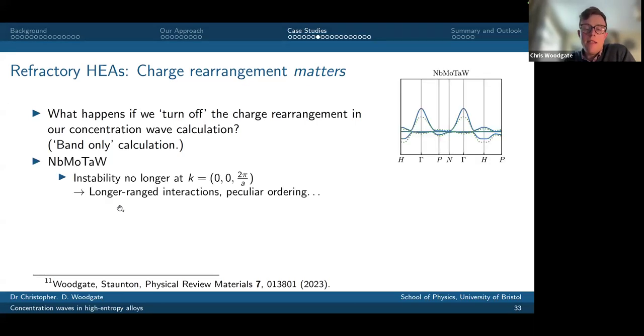And if I go to niobium, molybdenum, tantalum, tungsten, what I find is if I turn off the charge rearrangement, the ordering temperature is not particularly strongly affected. But what you find is the minimum eigenvalue no longer occurs at (0, 0, 2 pi over a). It's moved to some point a little bit away from the H point, which is kind of suggestive of maybe longer ranged interactions and a slightly more peculiar ordering. So that's kind of interesting.